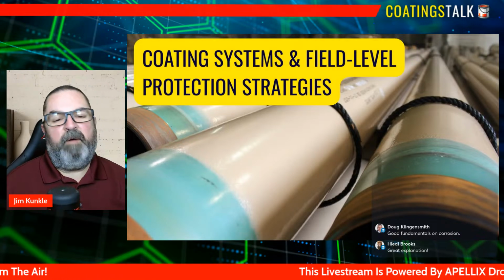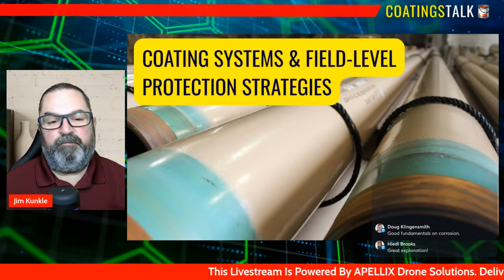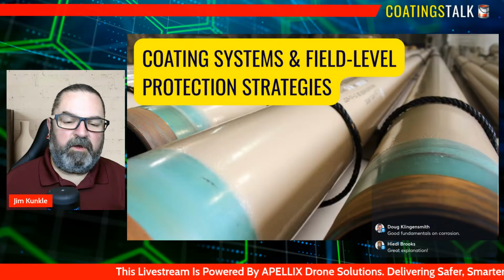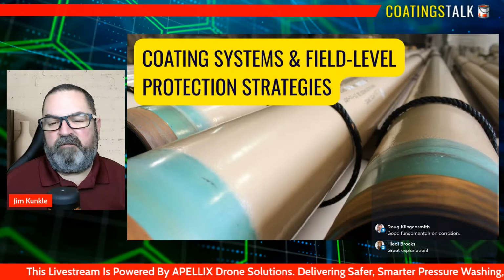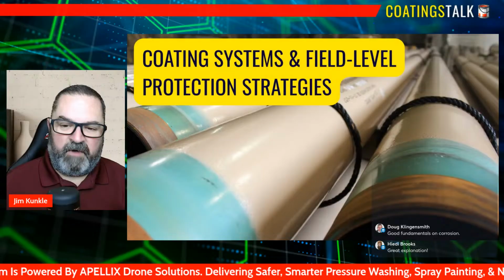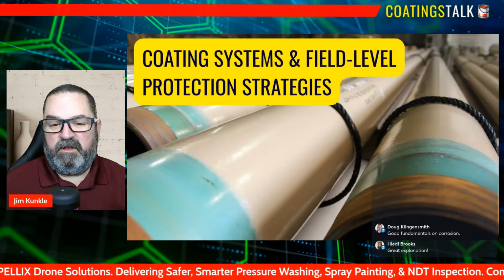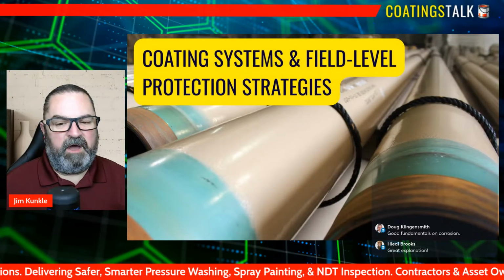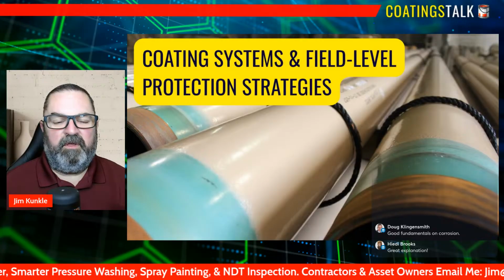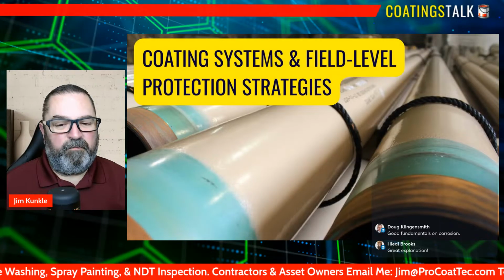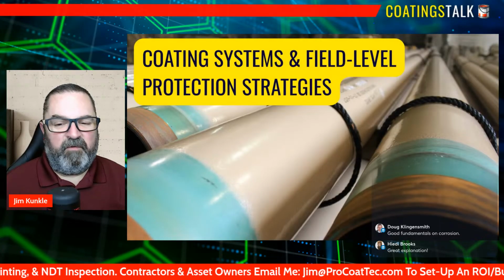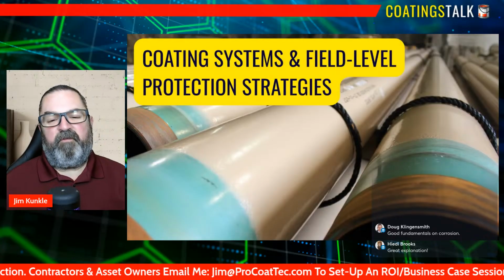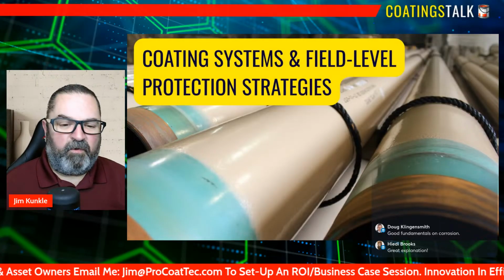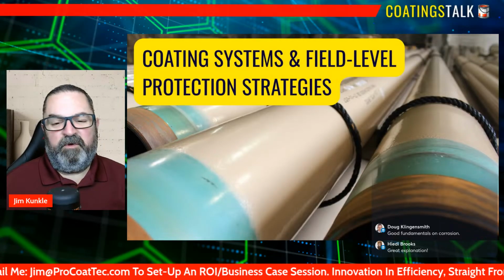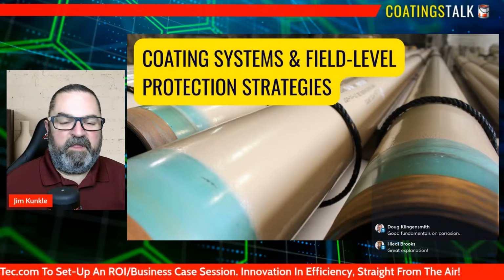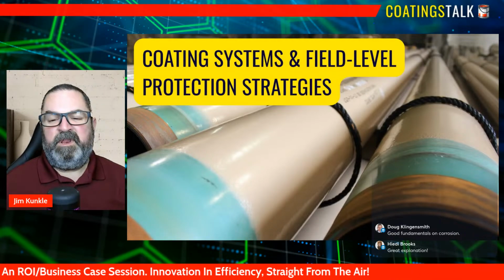Now, here are some common field mistakes and how to avoid them. Common field mistakes often stem from rushing, improvising, or assuming that a small deviation doesn't matter. But in coatings work, the smallest misstep could become the root cause of a major failure. And one of the most frequent issues is inadequate surface preparation. When contaminants, rust, or mill scale remain on the steel, they create weak points where corrosion can immediately restart beneath the coating system.